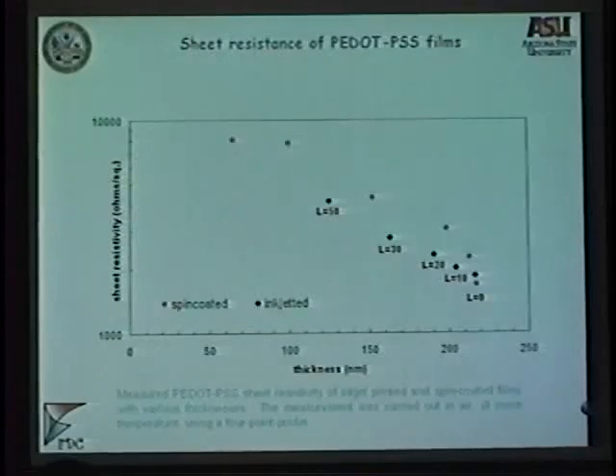If you compare this achievement here to spin coating, we tried our best to maintain the thickness as close as possible to the spin coating thicknesses. Spin coating is really an established technology, and if you know the ink viscosity and the spinning speed, you could very easily predict the thickness of your final film. It is not so easy predicting the thickness of the film in inkjet. It's still a brand new application that needs a lot of studying and technology development in order to understand, for a given ink viscosity and ink chemistry, how many drops do I need to put down in order to get 50 nanometers.